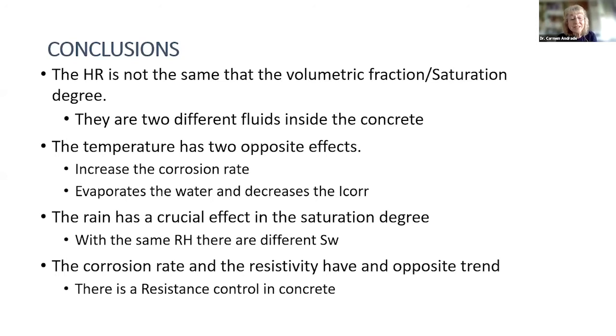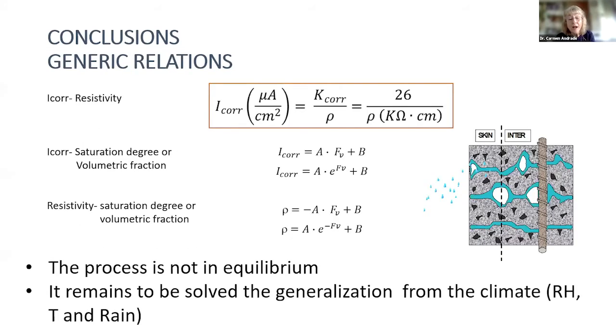The rain has a crucial effect on the saturation degree, and with the same relative humidity, there are several saturation degrees. The corrosion rate and the resistivity have an opposite trend, and there is a resistance control in the concrete. And from this moment, we have these empirical relations, and you can express the corrosion rate as a function of the resistivity, but also as a function of the volumetric fraction.